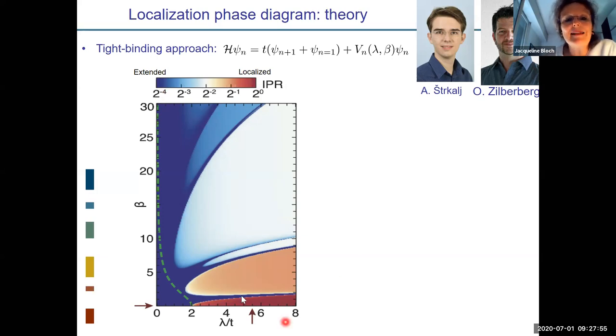What we discover here is that if we start from the localized part of the Aubry-André model, very red, and you progressively increase beta, it does not change continuously. There are some lobes, which are blue, which means that the states suddenly delocalize and then relocalize again, and then delocalize and relocalize again. So there is a cascade of delocalization transitions. This is the way the states evolve from localized to critical.